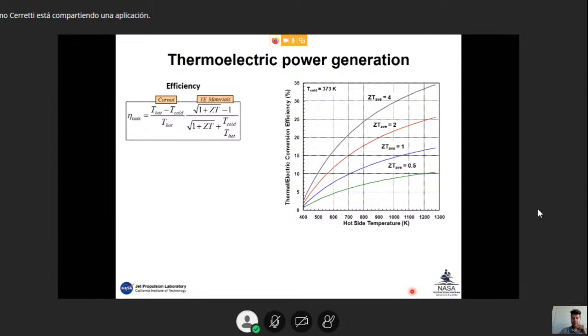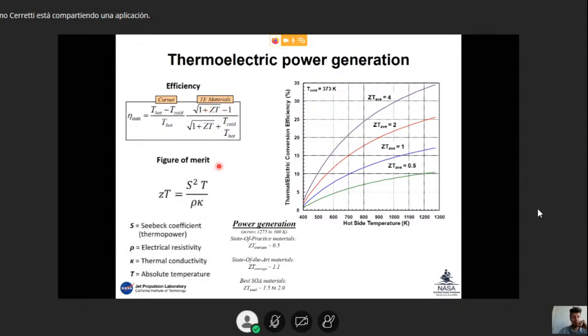So the Seebeck effect is what we use when we want to generate power. A thermoelectric power generator uses this equation for the efficiency. You can see that the first term is the Carnot efficiency. I'm sorry for the noise. And the second term is linked to the thermoelectric materials. We have the ZT, which is the figure of merit,